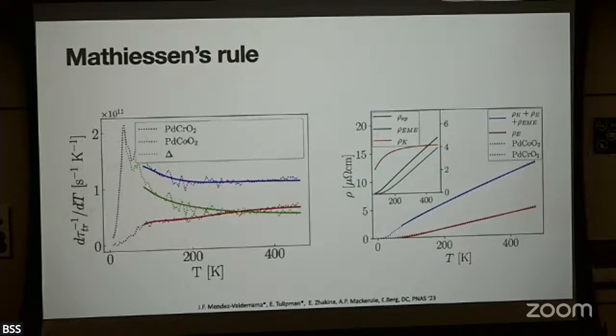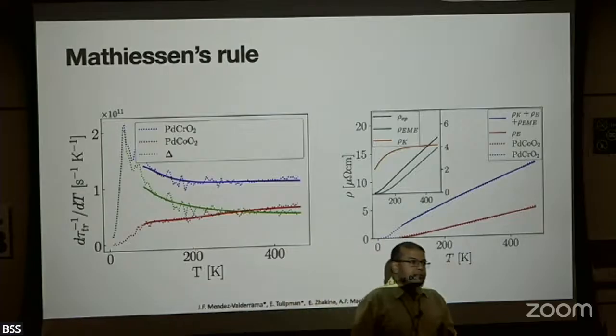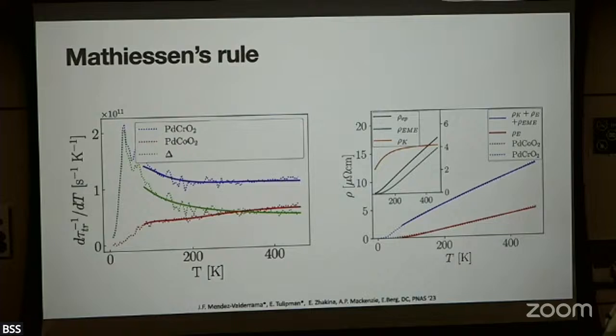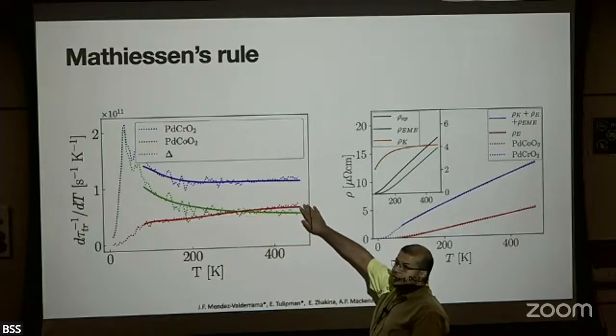So the interesting thing that I want to highlight is the following. What I'm plotting here are the computed scattering rates that you would get just from purely electron-phonon scattering, and the combination of the Kondo scattering, the electron magnetoelastic scattering, and so on. Now, if what we want to explain is this green curve, that's the difference between cobalt oxide and chromium oxide, if that was the only T-linear contribution in the story, then you would have expected a straight line. But it's not. What you're really seeing is palladium cobalt oxide is doing this weird thing.